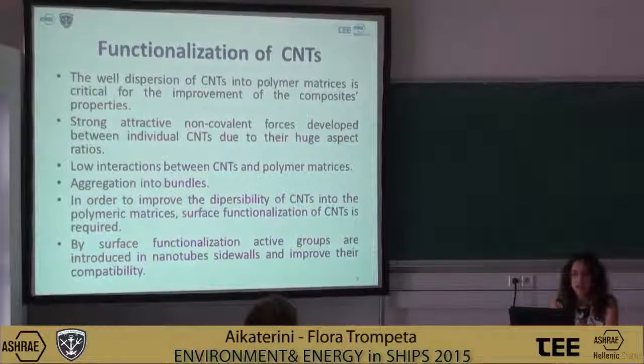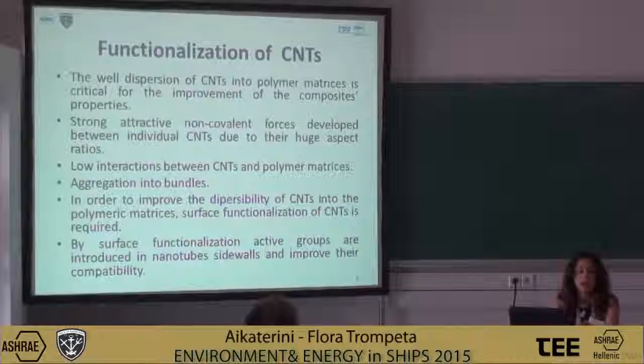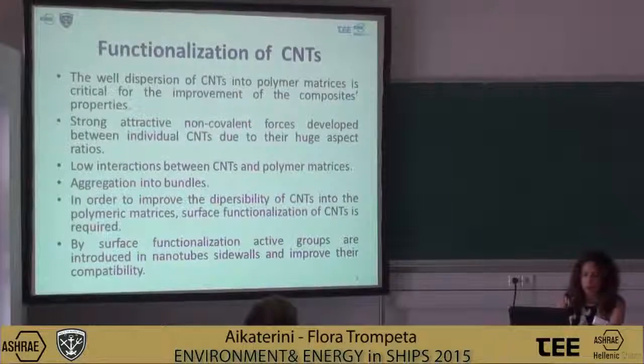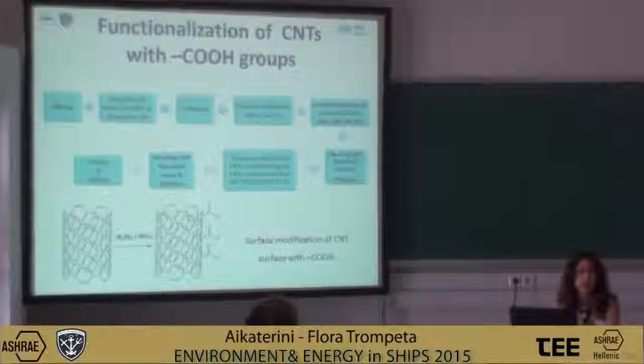The good dispersion of CNTs into polymer matrices is critical for the improvement of the composite properties. That's because we have strong attractive non-covalent forces that are developing between the individual CNTs due to their huge aspect ratios. These forces lead to low interactions between CNTs and polymer matrices and can lead to the aggregation into bundles. So in order to improve the dispersibility of CNTs into the polymer matrices, surface functionalization of CNTs is needed. By the surface functionalization, we can add active groups on the sidewalls of the CNTs in order to improve their compatibility with the polymer. In this study, we tested two different functionalizations.